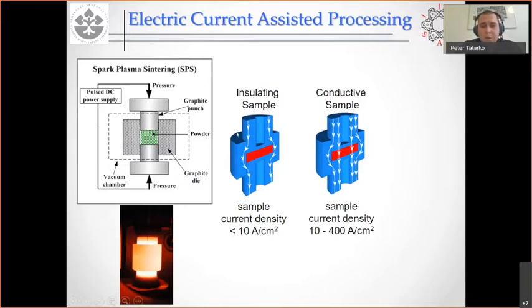And in case you have an insulating sample, the electric current goes through the graphite punch and graphite die, and then heats up the sample indirectly. In case you have a conductive sample, then you have a combination of both direct heating and indirect heating. For today's presentation, I will call these processes SPS joining.